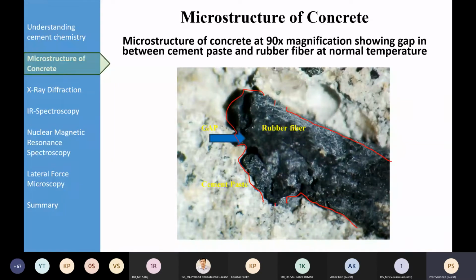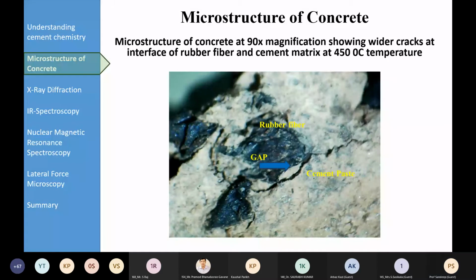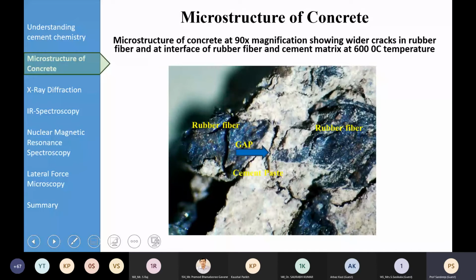Then we increased the temperature of the rubberized concrete slightly, and we tried to study the images at different temperatures. Here, when it was subjected to 450 degrees centigrade, you can see there's a gap now between the cement paste and rubber fiber. And when we went to 600 degrees centigrade, this gap increased. Again, this is the rubber fiber. There is internal cracking within the rubber fiber also, and the gap between the rubber fiber and the cement matrix is also increasing at 600 degrees centigrade.